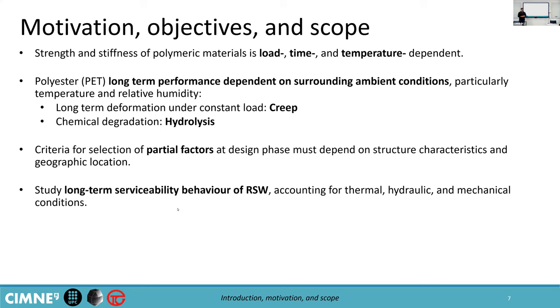Within the framework of polymeric materials, these types of materials have a strength and stiffness that is rate dependent. This means that their mechanical response will vary with temperature, with time, and with the applied load. Also, polymeric materials present, depending on the material, more or less creep. Creep is the long-term deformation over time under constant load, which can have serious consequences over the structure within its life cycle.